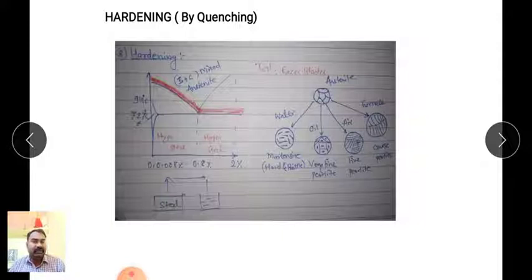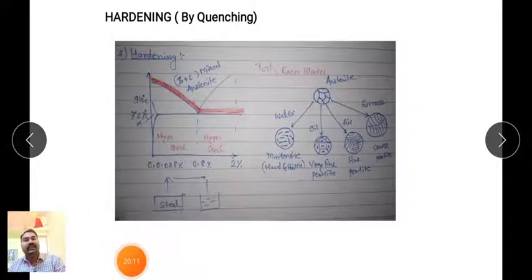But till now keep in mind that whatever hardening process we perform, it is performed on cutting tools and razor blades. Means the cutting ability of the tool must be more, and for that purpose we use the hardening heat treatment process. For hypoeutectoid steel we heat the steel above the upper critical temperature by 20 to 30 degrees Celsius. For hypereutectoid steel, we heat the steel component above the lower critical temperature by 20 to 30 degrees Celsius. Okay, and that temperature is maintained depending upon the thickness of the specimen. So this is nothing but the hardening heat treatment process.